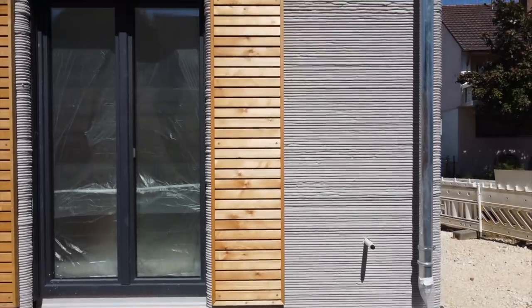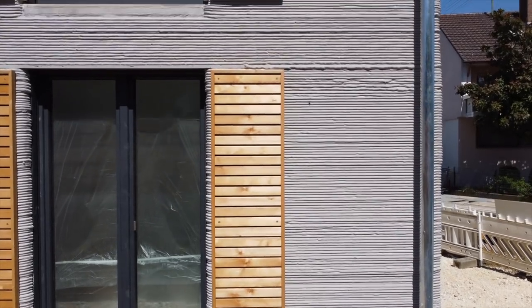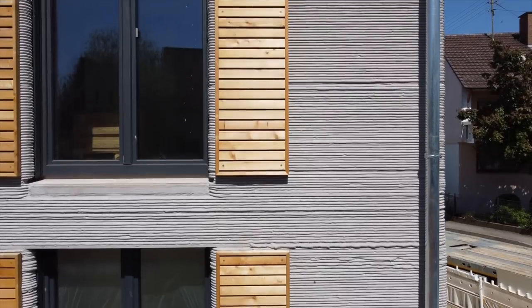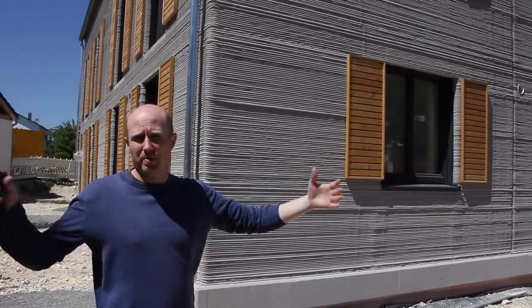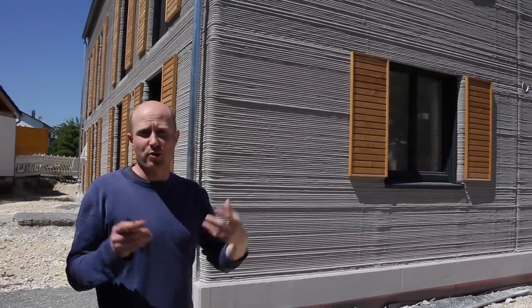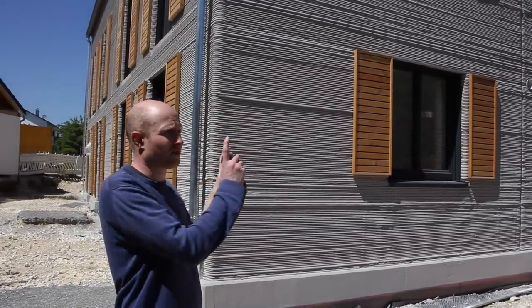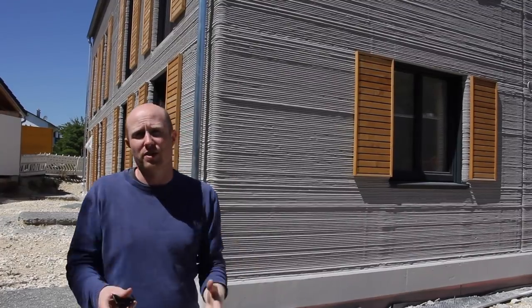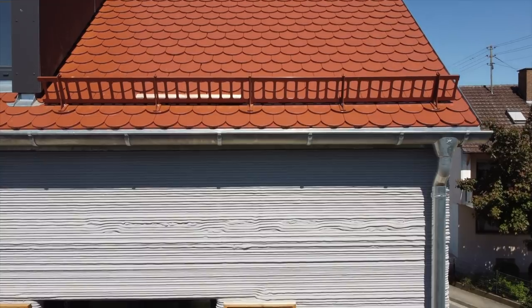Together with the material from Heidelberg we had to do quite a lot of testing in the printed form — not just small samples tested for compression or flexural strength, but whole wall elements: 8 feet by 8 feet wall elements. We had to do three-point bending tests, test the facade elements, test for freezing and thawing — quite a lot of testing which is now luckily copy-and-pasteable to other buildings that we will do.